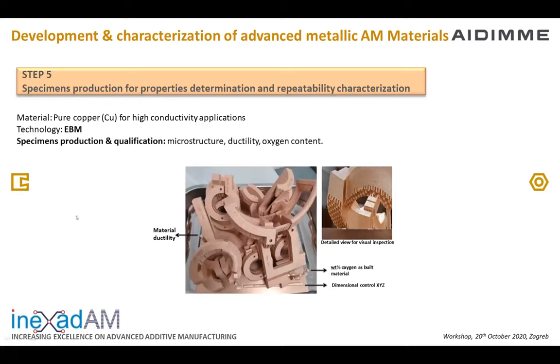Another example, for pure copper, for high conductivity applications, also in the EBM technology, after designing our operational procedure, we have learned that for this application, we need to control the material ductility. It's important, so we put here a tester to analyze this, as well as the oxygen content and the dimensional control. So this is our build production for qualifying the processing of pure copper.